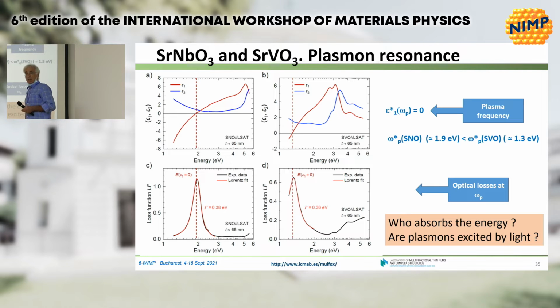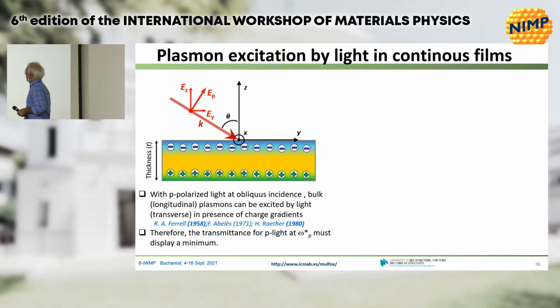Here is the absorption peak. This is the imaginary part, the part of the optical absorption at this frequency. It's clear that there is an absorption peak. Which is the physical origin of this absorption? This is why I put here, who absorbs the energy? Are plasmons excited by light? And that brings me back to the question of Kittel's book I was joking about before.